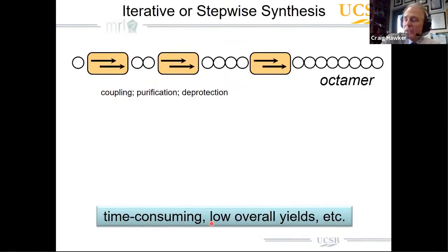If we look at how Kenichi did this work, he started with the monomer, made the dimer, then did protection, deprotection chemistry to couple two dimers to give a tetramer, protection, deprotection chemistry, coupling to give the octamer, and so forth. So it really is a stepwise process. It's hard to get odd numbered materials. It's also hard just to make materials, as I say, time consuming and low yields.